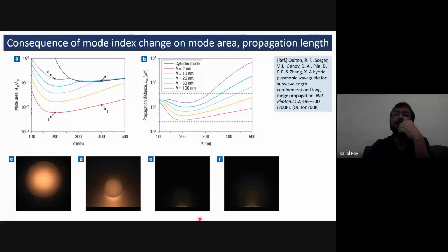This phenomenon is represented by the mode area, which is basically the effective area within which most of the energy is confined. You can see the mode area, normalized by the area when it is not interacting with the metal plate, can be like 100 times smaller when the dielectric and metal are placed only a few nanometers apart. And definitely it has a consequence.